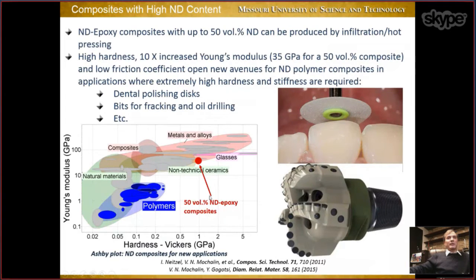This composite, nanodiamond epoxy composite, is somewhere here in this diagram, which shows the different materials plotted in terms of their Young's modulus as a function of hardness. And you see that typically polymers are very much to the left compared to our material. So our nanodiamond polymer composite is close to glasses, close to metals and alloys, okay? It has very high mechanical properties. So any applications where you use metals, alloys, glasses, you can potentially use this composite. For example, some of them are shown here. You can make bits for oil drilling and so on.